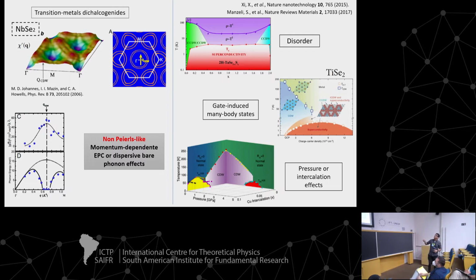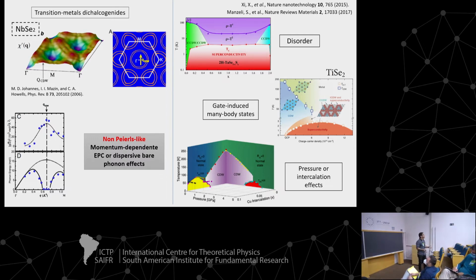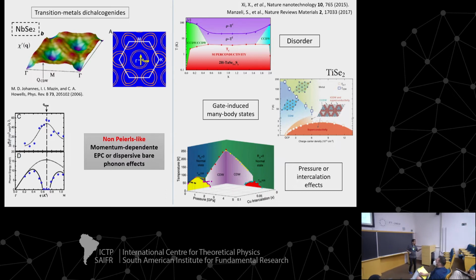Still concerning this transition metal chalcogenides, we can adjust such kind of phase in many ways. For instance, by disorder, by gate-induced doping, by pressure, and then we can create whole, rich phase diagrams by this kind of adjustments. And again, all of these phases here, in principle, these charge density wave phases are not conventional in the sense that we cannot explain them by the Peierls mechanism.